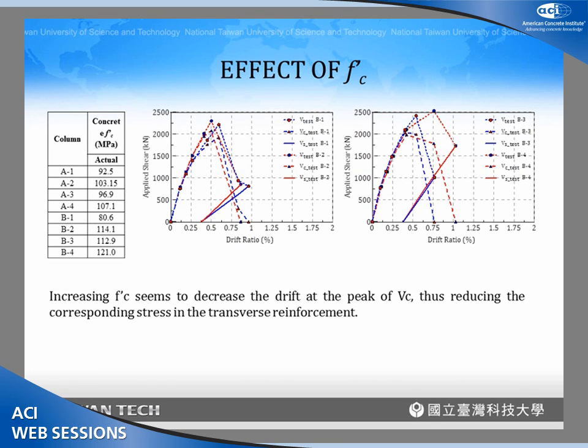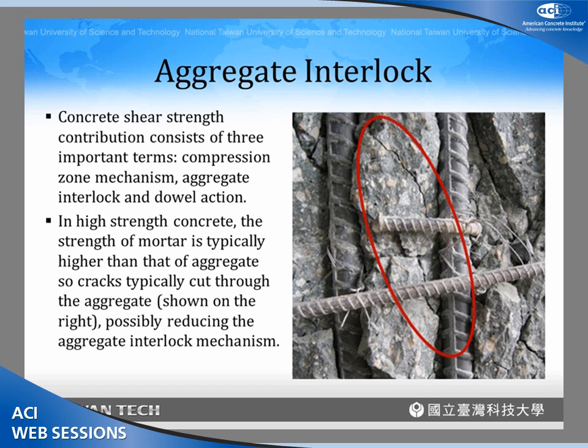It seems to me that when we increase the f'c, we decrease the drift at the peak of the concrete shear strength. This means that because of the reduced drift, the stress in the transverse reinforcement also reduced. So this may imply that when we increase the concrete compressive strength, you are going to reduce the stress in the transverse reinforcement when the concrete reaches the peak of the shear strength.